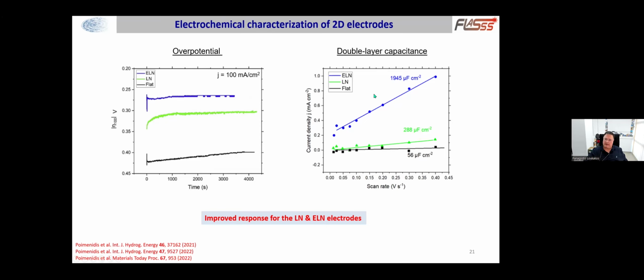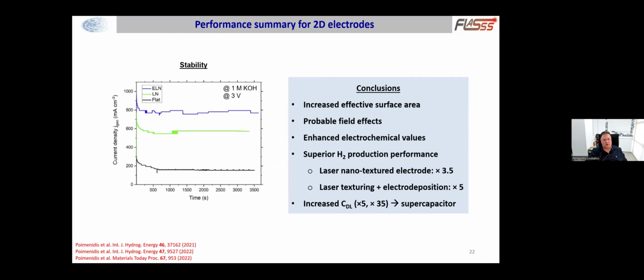Also, when looking at the double layer capacitance, we can see again that the laser nanostructured electrodes behave much better than the flat electrodes, which makes these electrodes very interesting for applications in supercapacitors. Also, the stability, the performance of these electrodes over time is very important when thinking of applications. Here we have examined these electrodes for only a few hours, but even when testing them again several months after their fabrication, we found the same performance. So this is also a very important result.